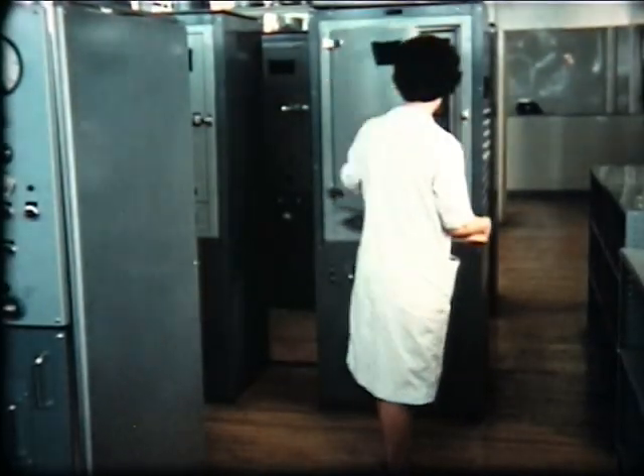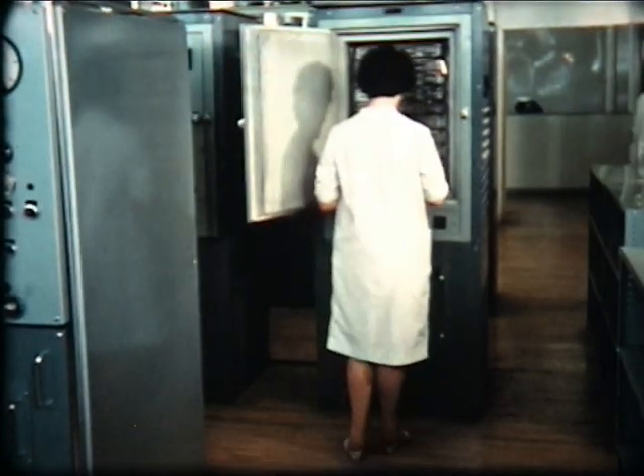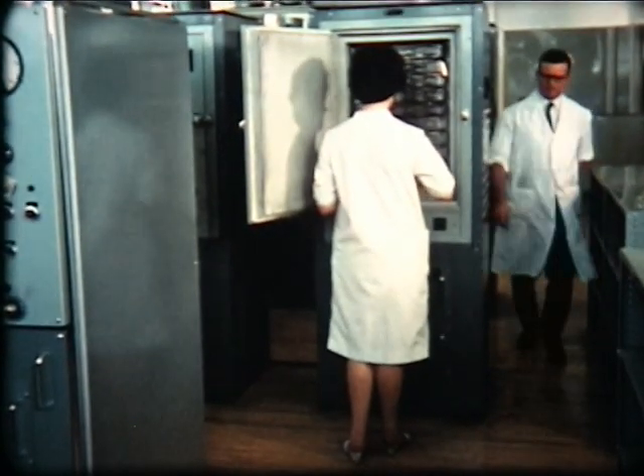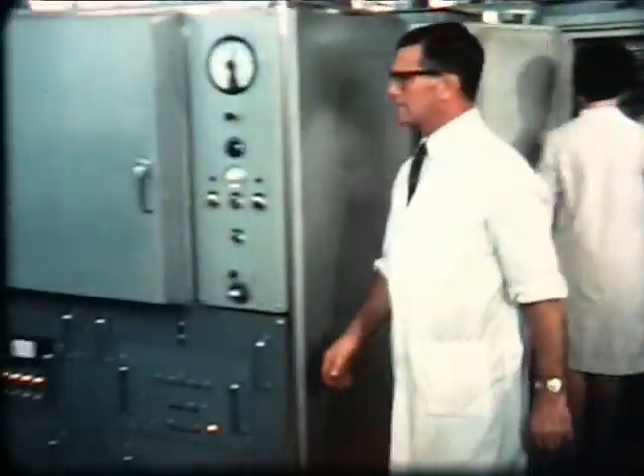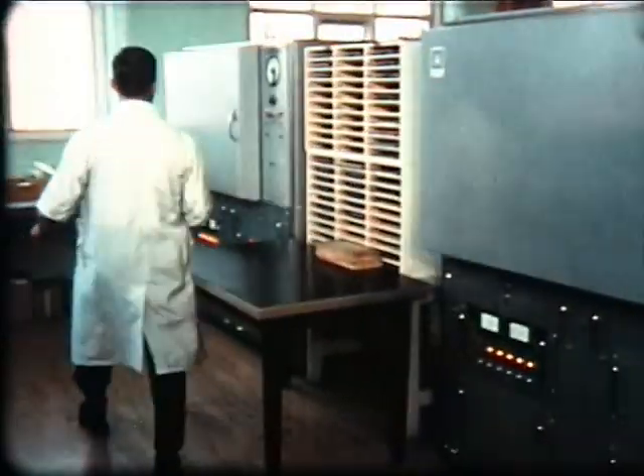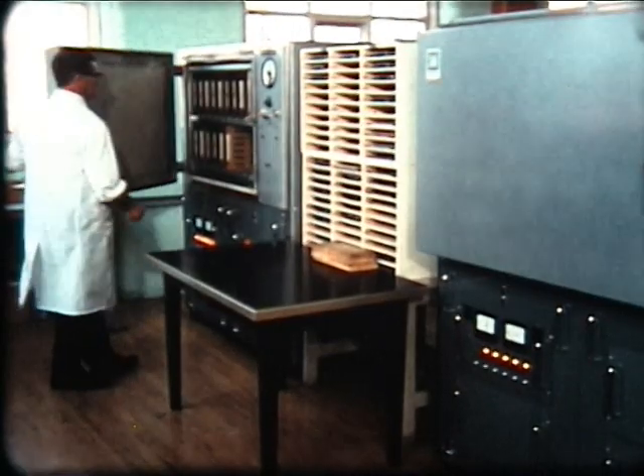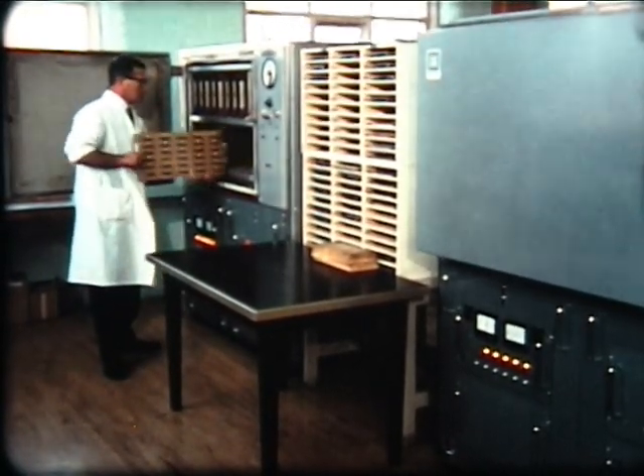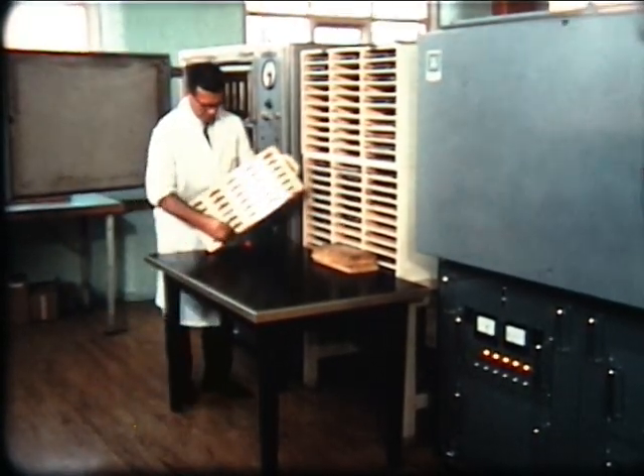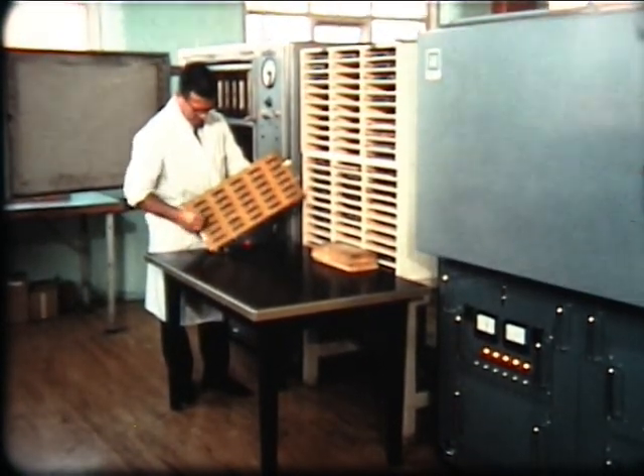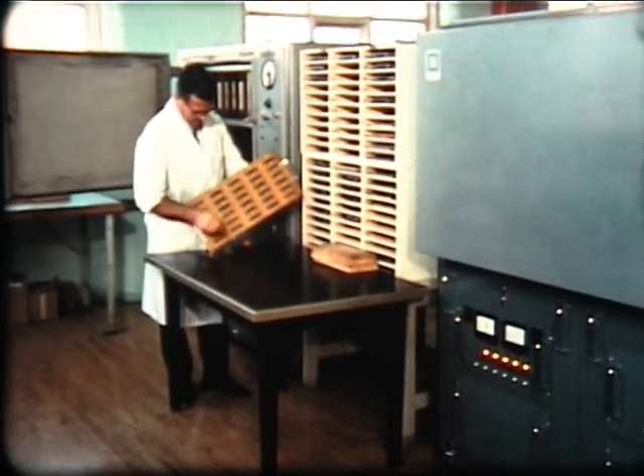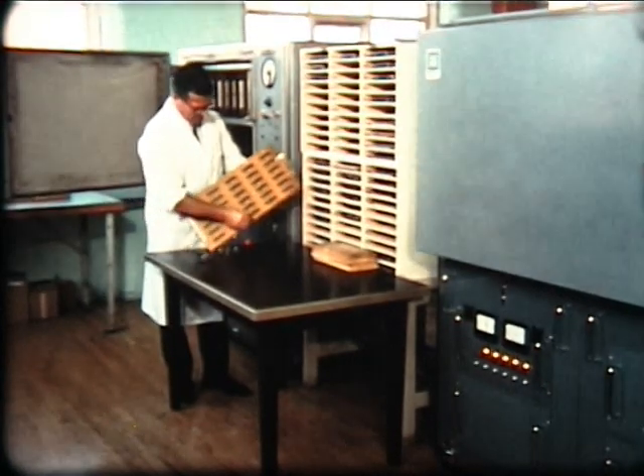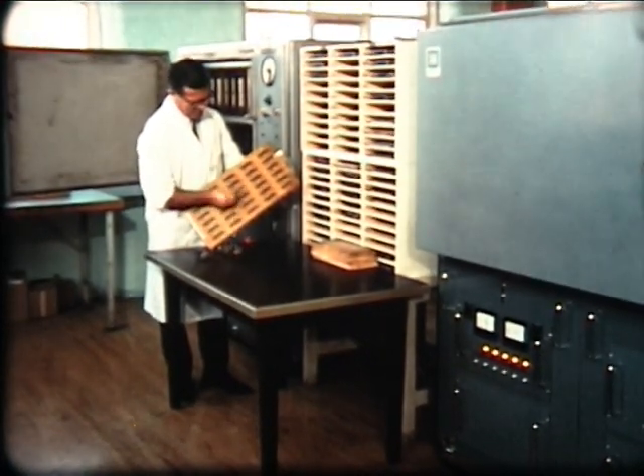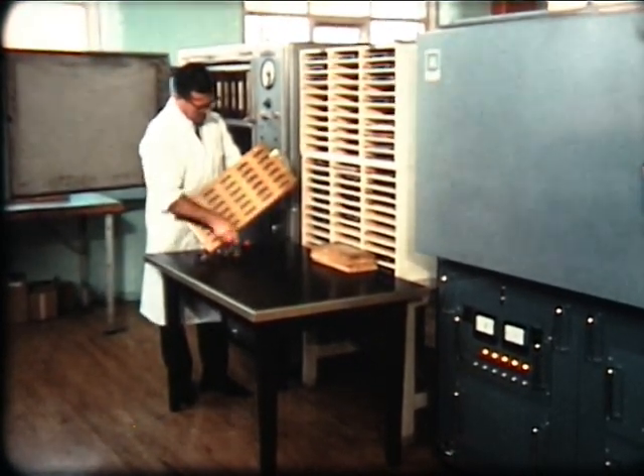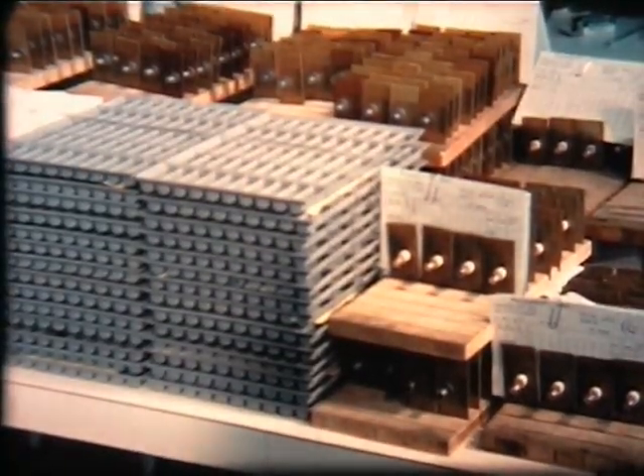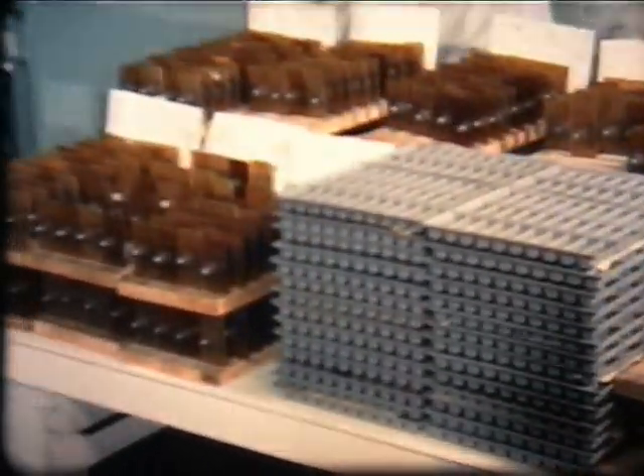When the assembly processes are completed, integrated circuits enter a phase of exhaustive electrical testing. In aging racks, they are run for up to 48 hours under conditions of temperature and dissipation much more severe than any they are likely to encounter in use. The plug-in modules used in these racks allow hundreds of circuits of different types to be processed at the same time. Before and after aging, every circuit is tested electrically for leakage currents, operating times, and other characteristics.